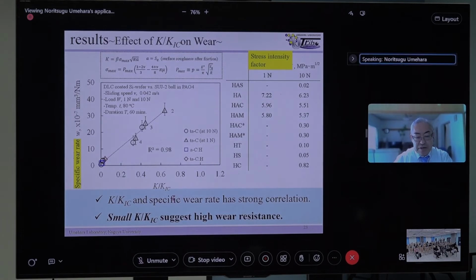So if we use K by K1C, finally we can get only one line, one tendency, like this. K by K1C and the specific wear rate have a strong correlation. So it's not only K1C. K1C is a material property, while the K value comes from friction properties, like the friction coefficient. K also increases with surface roughness. If the roughness is large, the K value is also large. So a small K by K1C suggests high wear resistance.